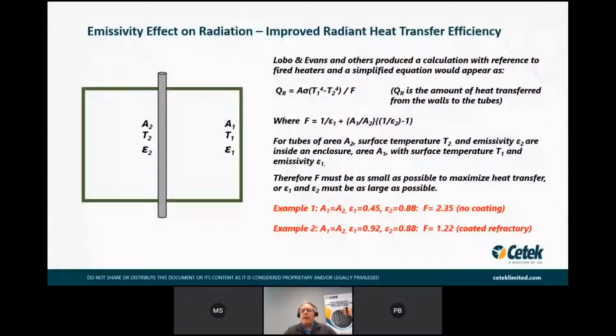I did want to touch on some of the background calculations, if you will. Lobo and Evans and others have produced this mathematical explanation in terms of high emissivity coatings, how they actually work, and how it improves the radiant heat transfer from a refractory surface to the tubes. Now, to be fair, this calculation does not consider the radiant heat going directly from the flame or flue gas to the tubes. But in this calculation, it does show how the radiant heat from the walls can essentially be doubled. So to maximize QR, or the heat transfer, F must be minimized.